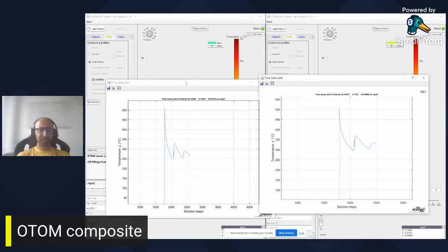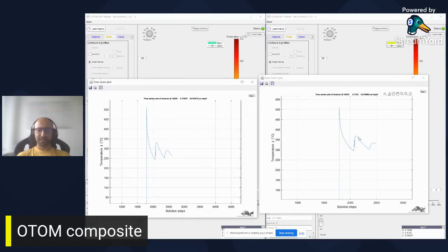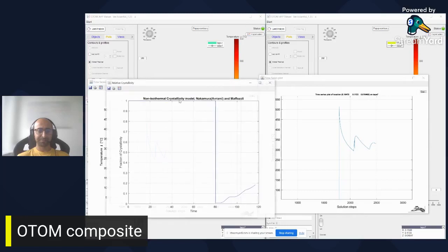So if you look at these two temperatures, you will see that for the right side, which is base tooling of 140 degrees Celsius, we are very close to the melting and very close to the liquid phase, which is 340 degrees Celsius. And in the liquid phase, the material is starting the crystallization, and probably there would not be so much time for crystallization growth here.